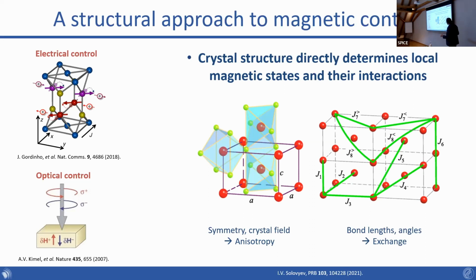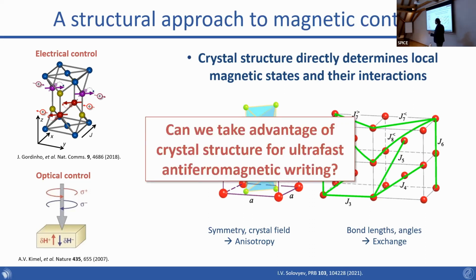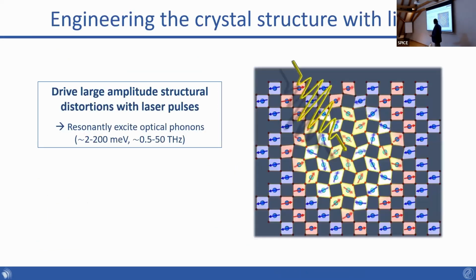So the question that I will try to address is can we take advantage of this strong coupling between the magnetism and the crystal structure to achieve the goal of this conference, which is ultrafast antiferromagnetic writing. And to do that, we developed this approach in Hamburg where we essentially dynamically excite the crystal lattice, dynamically drive the crystal lattice by resonantly exciting vibrational modes of the material with optical pulses. And essentially these are the optical phonons in the material that couple to light. And they have frequencies in the few terahertz to mid-infrared frequency range.